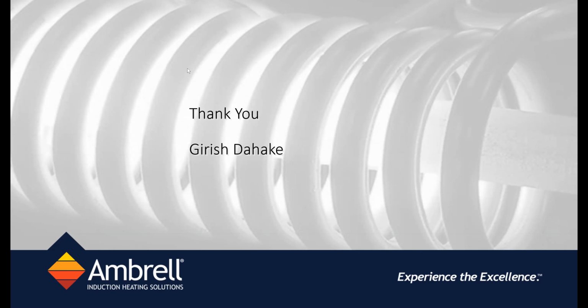All right, and the next question ties in a little bit to an earlier question, and that is, what would happen if a part were to come in contact with a winding? Some of your images show the parts very close to the windings. Excellent question. Typically, we do not want the metal part to come in contact with the copper windings of the coil. This is where, again, the design of the holding fixture comes into play. Given the tolerance of the holding fixture, you have to design the induction heating coil with the appropriate clearances. If the holding fixture can move, let's say, for example, 1 or 2 millimeters, or let's say 1/8 inch, then you have to make sure that the coil is at least 1/8 inch away so that the part can never come in contact with the coil.